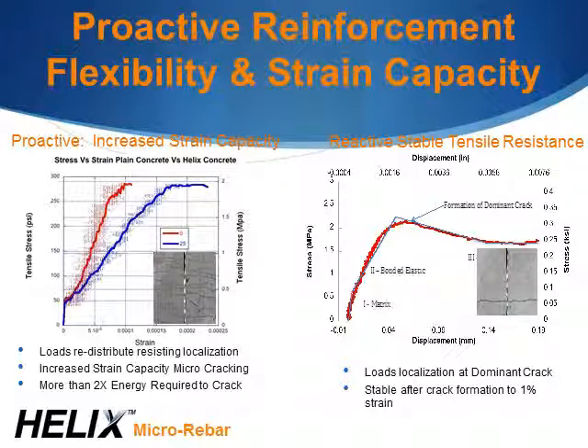Also, you can calculate the amount of energy that it takes to form a dominant crack in the concrete, and that's the amount of area that's under the red curve or the blue curve. And that area is more than twice with even a small dosage of Helix than it is with just standard plain concrete. And not even rebar does anything to the concrete in this phase. The reason this is happening is because Helix has a very efficient bond and doesn't let go, that twisted shape acting in essence like a screw instead of a nail. It just doesn't allow itself to move, and it functions at a much smaller scale than rebar. So you're getting contribution of the reinforcement even before that dominant crack forms.